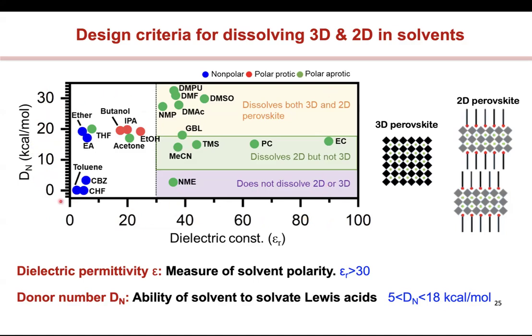And you can see there are all these different solvents that we've listed: non-polar solvents, polar protic solvents, polar aprotic solvents. And so it turns out that there are these sets of solvents which are below a certain dielectric constant, which do not dissolve any of the perovskites. Acetone, IPA, they don't dissolve it. But if you look at these solvents, these polar aprotic solvents, things like DMF and DMSO and DMPU, all these derivatives. It turns out that these green dots here, which are above the dielectric constant of 30 and above a donor Gutmann number of 18, can dissolve both the 3D and the 2D perovskite, which means I can take these precursors, put them in, and they really dissolve away your 3D and 2D both.